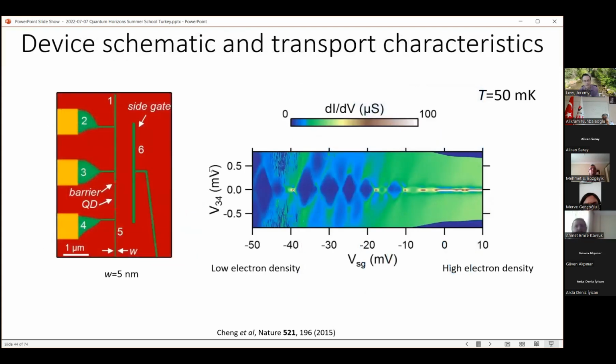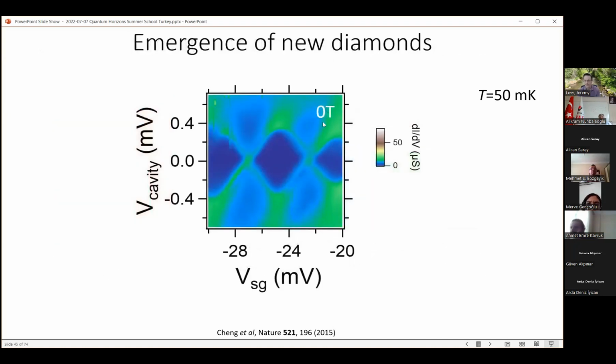So this is a single electron transistor created from this oxide interface. This is typical data, and you can see these diamonds, right? So this is, again, the source drain bias and the gate bias. There's actually a superconducting regime here. These measurements were made at 50 millikelvin in a dilution refrigerator. And what I want to do is focus on one of these diamonds. So this is zero magnetic field, and I'm going to increase the magnetic field 1 Tesla at a time. So if I go 0 Tesla, 1 Tesla, 2 Tesla, there are some subtle differences, but it's not that remarkable.